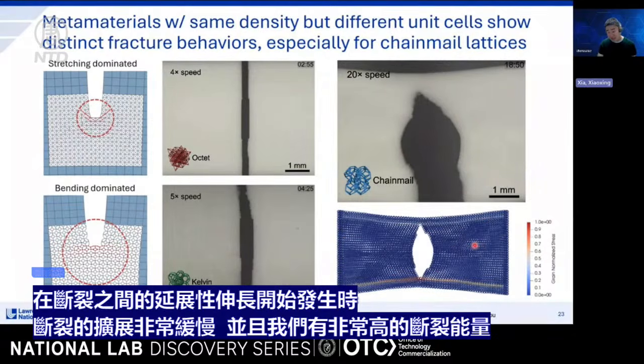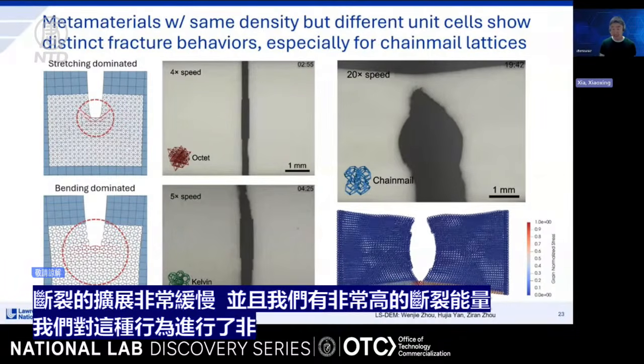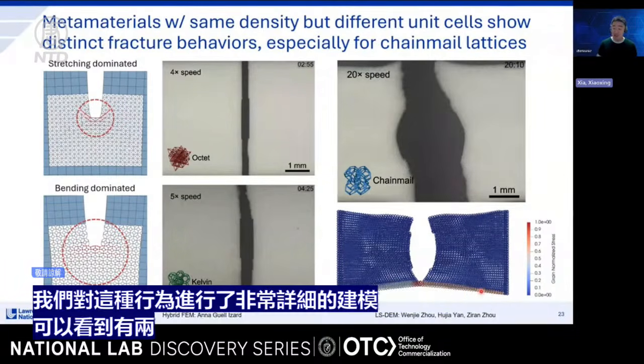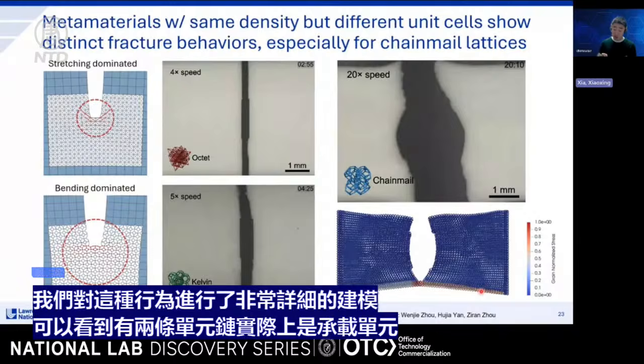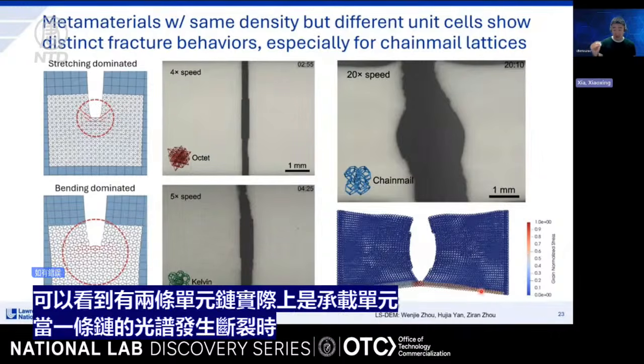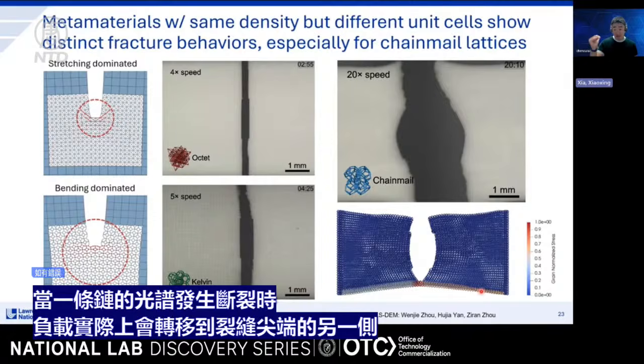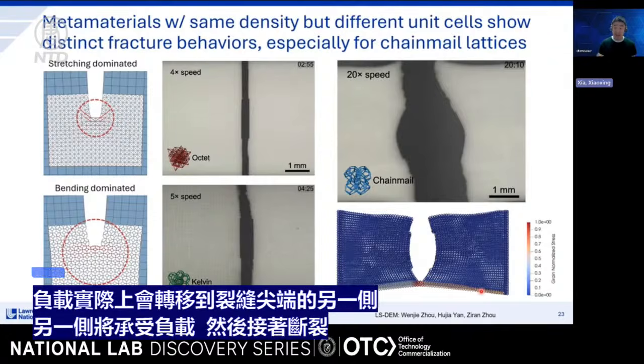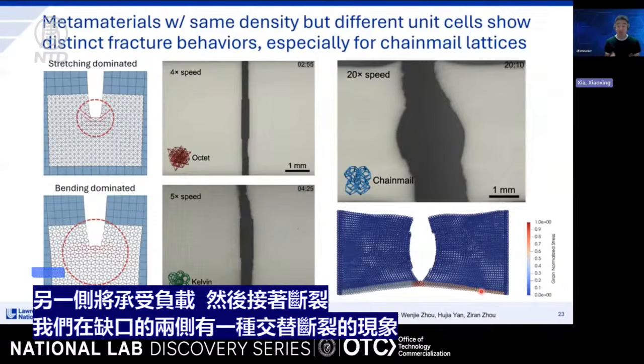You can see that there are 2 chains of units that are load-bearing. So when one chain is fractured, the load shifts to the other side of the crack tip, and the other side will hold the load and then fracture next. So we have a kind of alternating breakage at two sides of the notch. And this is really fundamentally new mechanical behavior that is controlled by the local microstructure.